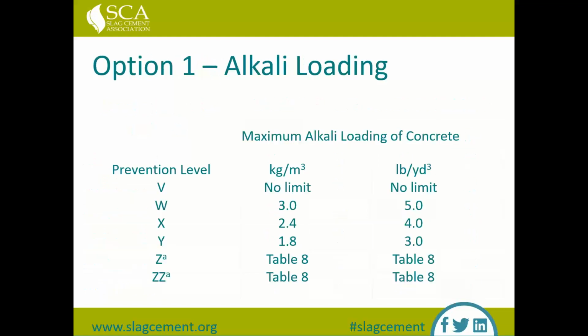The first prescriptive option for mitigating ASR is alkali loading. With the different prevention levels, we've got different maximum alkali loading of concrete: prevention level V has no limit, prevention level W is 5 pounds per cubic yard of alkalis, down to prevention level Y, a maximum of 3 pounds per cubic yard of alkalis. We'll look at Z and double Z a little bit later.